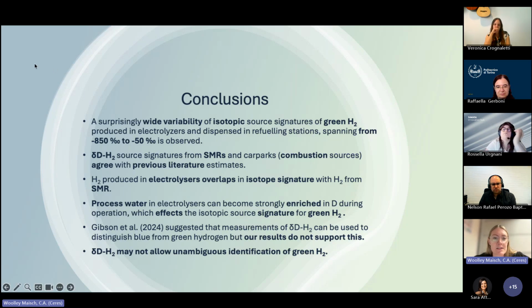So, to conclude, we had a surprisingly wide variability of isotopic source signatures of hydrogen produced in electrolyzers, spanning from -850 per mil to -50 per mil. However, the delta D source signatures from SMRs and car parks agree nicely with previous literature estimates, but we find that hydrogen produced in electrolyzers overlaps in isotopic source signature with hydrogen from the SMR, and this is because the process water in electrolyzers can become strongly enriched in deuterium during operation, which then affects the isotope signature of the green hydrogen. Gibson et al. suggested that measurements of delta D can be used to distinguish blue from green, but our results do not support this. So delta D may not allow for the unambiguous identification of green hydrogen.